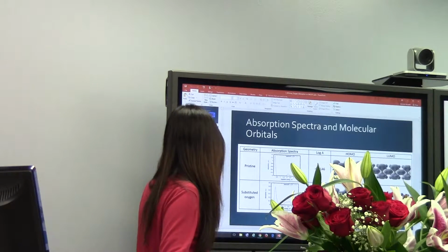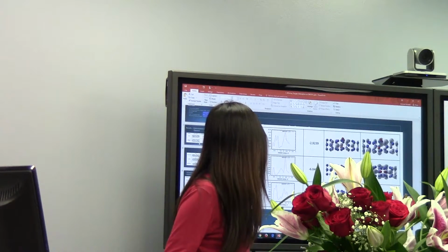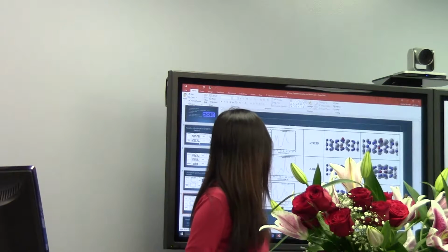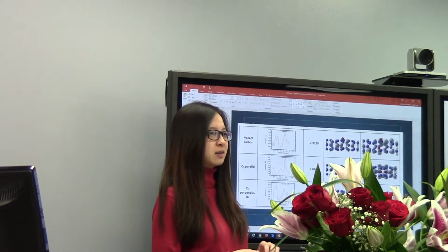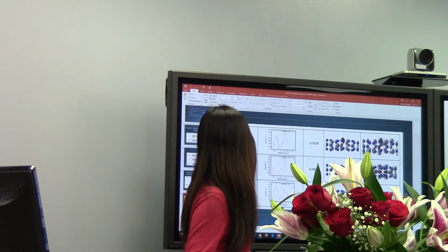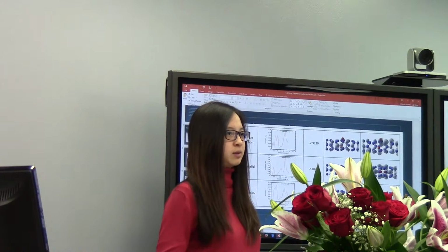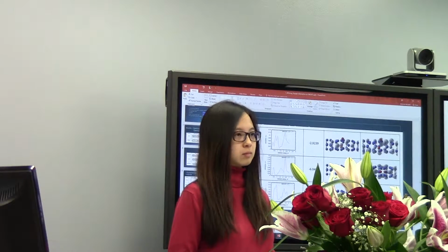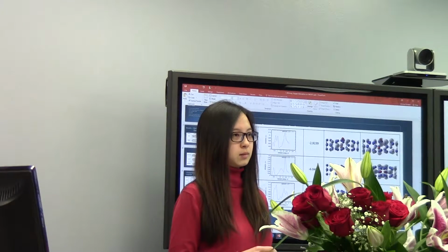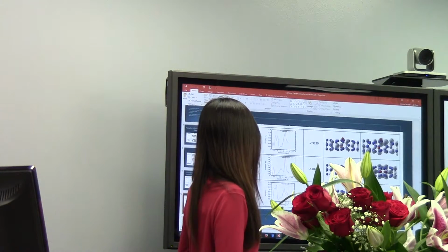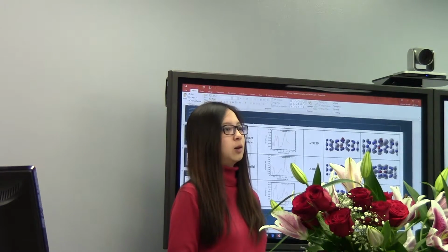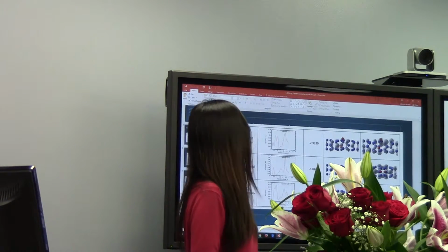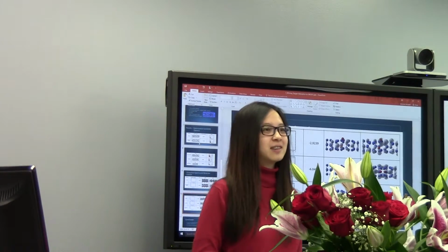For the HOMO and LUMO, it does not change a lot, except for this one. It has localized orbitals on the oxygen. In which case, when you substitute or when? No, the one that I put on top, just the normal. So when it's physisorbed, then you have very strongly localized orbitals, and these orbitals introduce these states inside the gap, right? In the other cases, when it's substituted, it's more delocalized over the surface, although the gap is still changing. Okay, so you have a different nature of these electronic states. Okay, thank you. Dr. Kuhn?